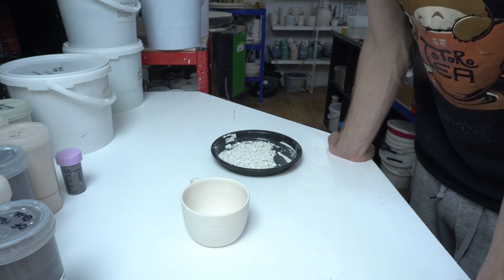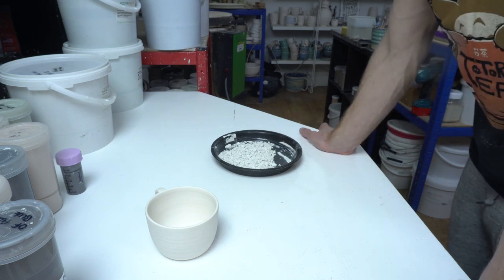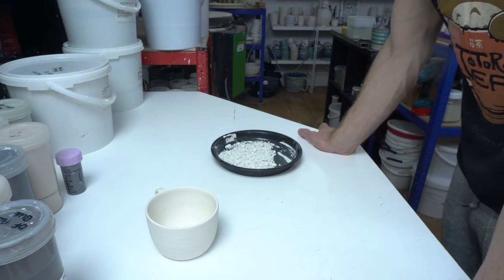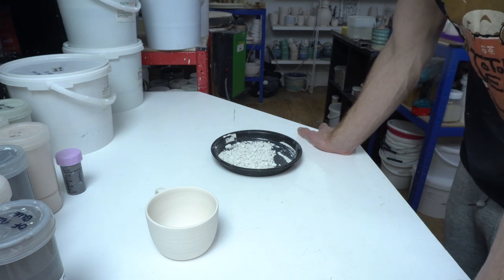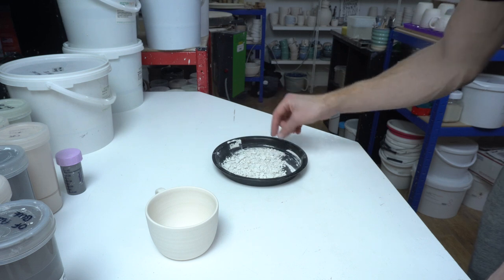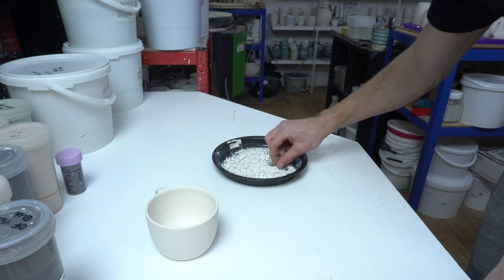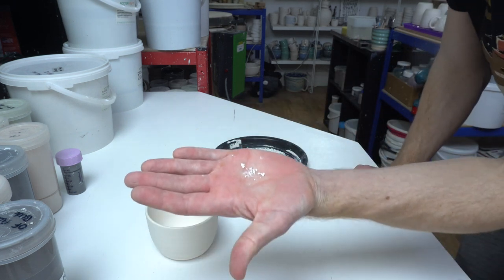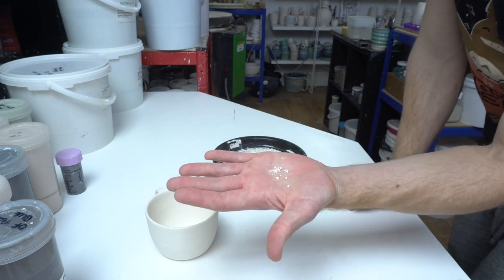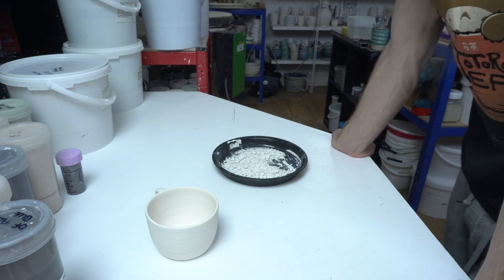And if you can find really coarse sieves, so you can sieve this grade and then sieve those to get an even bigger grade. Somewhere I have a glaze ingredient tub that I drilled 5mm holes in the lid of. If you shove those in the tub, you can shake them out and you'll get lumps with 5mm as a maximum dimension, which are probably a bit big for a normal glaze to keep in suspension, but a thick mix of glaze can just about do it. And they'll give you obviously much bigger bursts of that glaze.